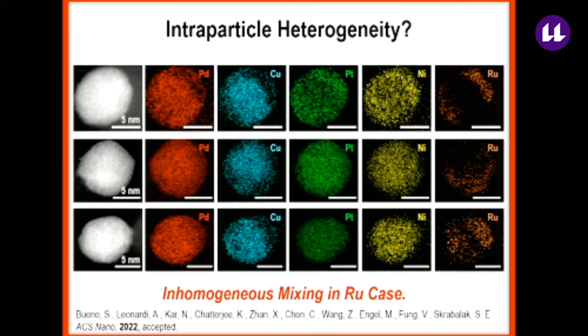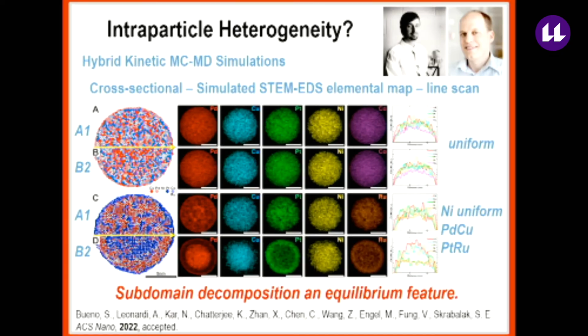And my student worked really hard trying lots of different conditions, heating for longer times, shorter times, higher temperature, lower temperature, different atmospheres, and we always got this result. And so we started to wonder if this was an inherent feature of this specific composition, or if there was some way that we could force better mixing. And again, this is where having great collaborators is quite helpful.